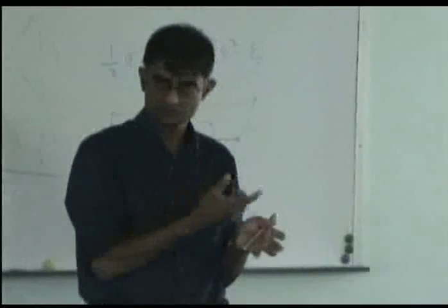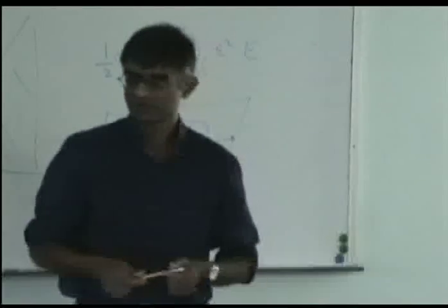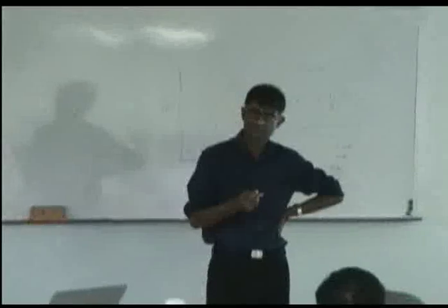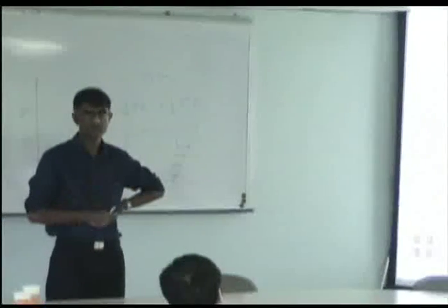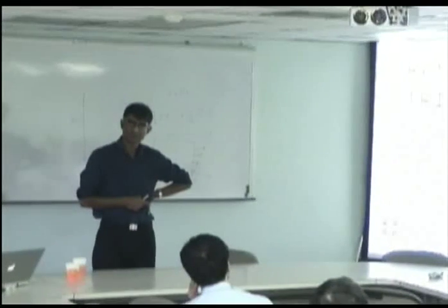0.15% carbon, 1.5% manganese, 1.5% silicon. The silicon is there to stop the precipitation of cementite so that the carbon remains in the austenite. And what I want to ask is, what is the role of transformation-induced plasticity in such steels? The conclusion I'm going to reach is that there's hardly any role of transformation-induced plasticity. But I need to show you how we reach that conclusion.